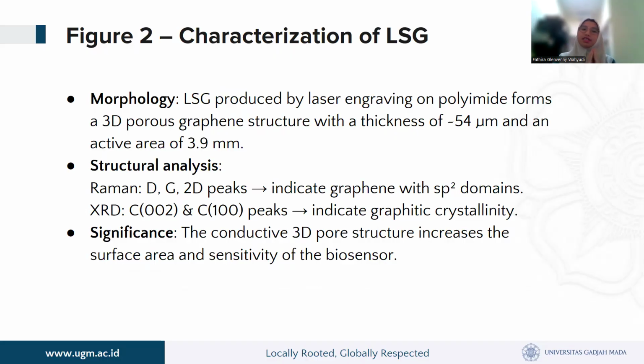This is the summary of figure 2, the characterization of LSG. Morphology: LSG produced by laser engraving on polyimide forms a 3D porous graphene structure with a thickness of 54 micrometers and an active area of 3.9 millimeters. Structural analysis used Raman and XRD. In Raman, we got D, G, and 2D peaks indicating graphene with sp2 domains, and XRD C(002) and C(100) peaks indicate graphitic crystallinity. Significance: the conductive 3D porous structure increases the surface area and sensitivity of the biosensor.